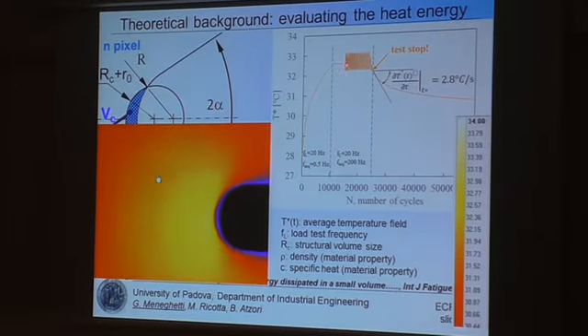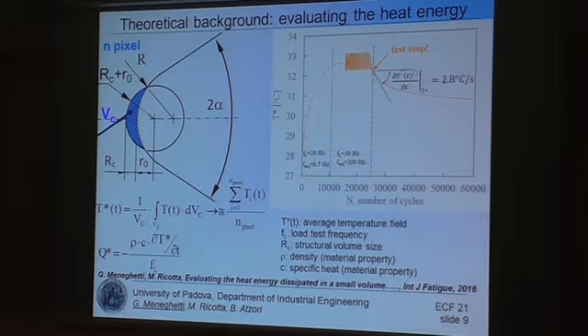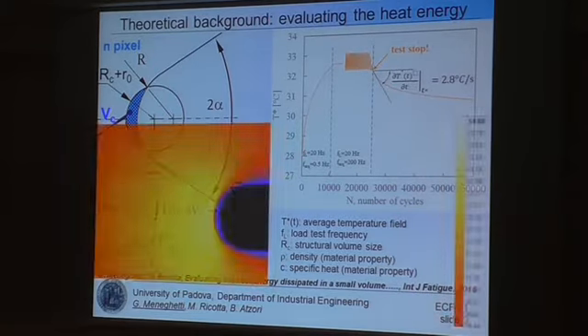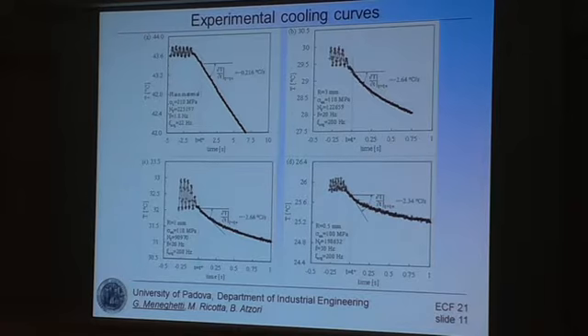You see here a video. We are in this case. You can see the thermoelastic effect superimposed to the mean temperature level. In a while, we should reach the point where the test is suddenly stopped and the material cools down. Yes, here we are. You can see the material cools down, and if you measure the thermal gradient during this cooling phase, you can estimate the energy dissipated as heat. Now, let's have a look at the experimental results.